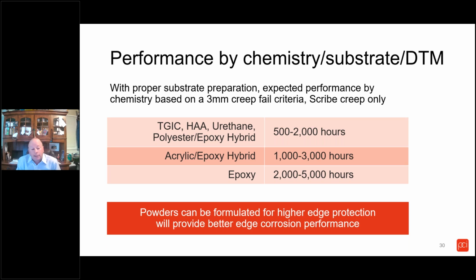Your TGICs, TGIC-free coatings, urethanes, and polyester epoxy hybrids will give you somewhere between 500 to 2,000 hours if you have an optimal substrate to apply to. Your acrylic epoxy hybrids will give you a little better performance, about 1,000 to 3,000 hours. And then the epoxy coatings will give you your best option at 2,000 to 5,000 hours on a properly pre-treated substrate.